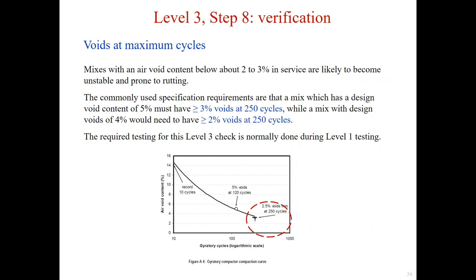Experience indicates that asphalt mixes with air void content less than 2 to 3% are likely to be unstable and prone to rutting. This is because the binder almost totally fills the void spaces and reduces aggregate particle interlock and friction. The specification requires the mix, which has a design air void content of 5%, to have greater or equal to 3% voids at 250 cycles.